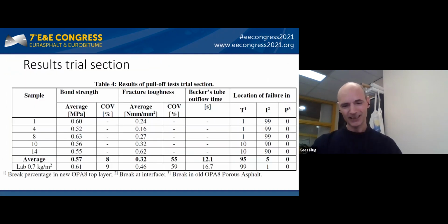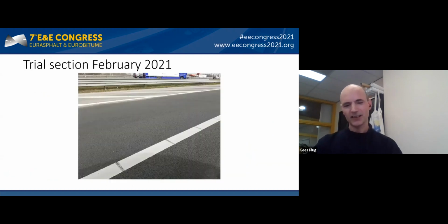For the test of the trial section, cores were drilled from the test section and tested the same way as the laboratory samples. As can be seen, the results are almost comparable with the laboratory samples. So the result was satisfactory. This picture shows the results in February 2021, and no disturbing things were visible. So it looks very promising.